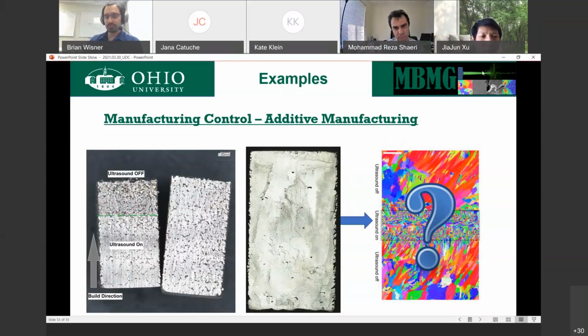So when you show the section below this green line, that means this structure is starting to solidify layer by layer during this process, but the ultrasound continues to propagate, and you see more voids as we get closer to the blue line, where the ultrasound gets less intense. Then when you move above the green line, that's where you had ultrasound completely off. Right? Correct. Okay, I see.